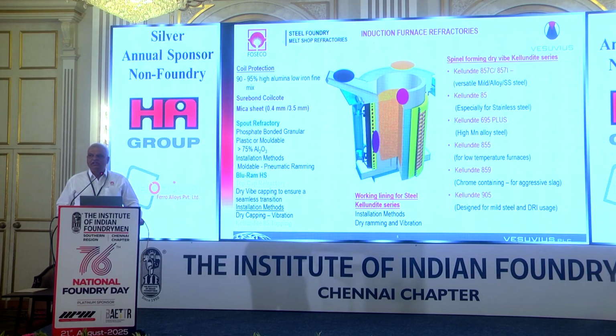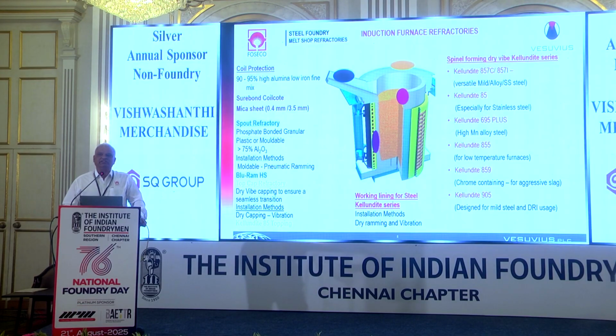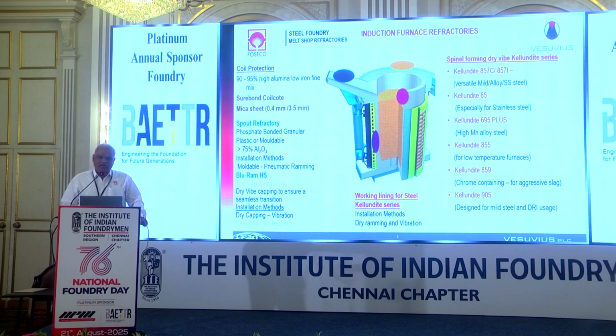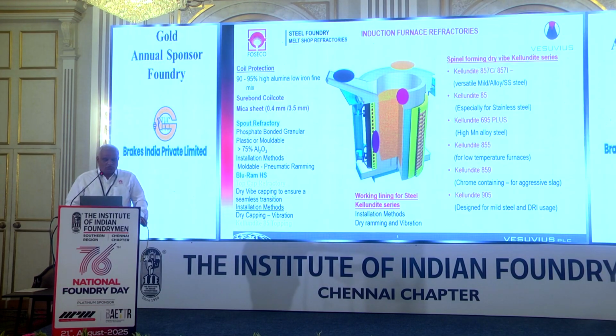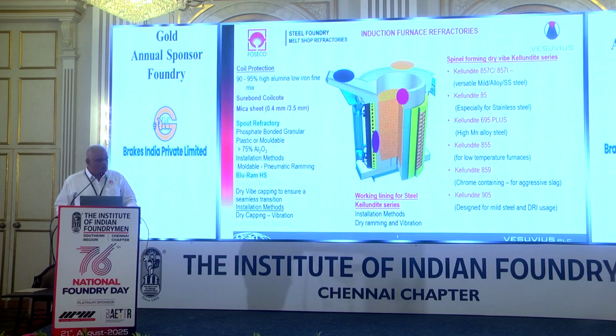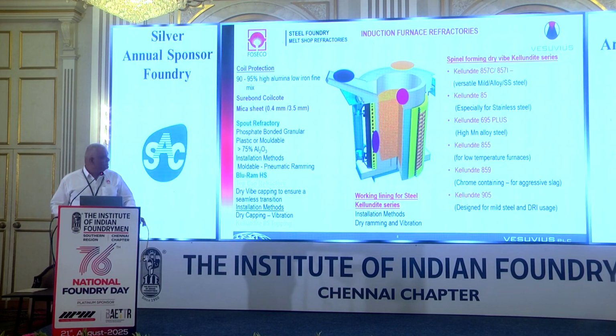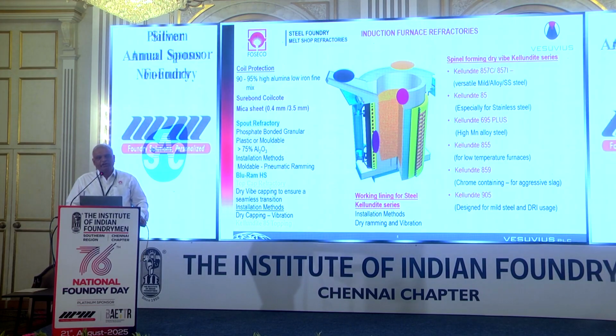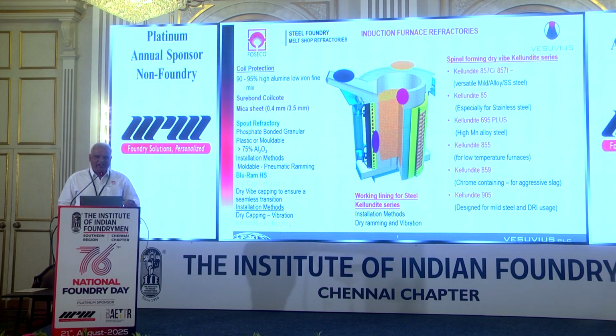They just sieve it and use it as a coil coat, but it is not advisable because in conventional castable the iron percentage is on the higher side. As this material is close to the coil, it requires lower Fe content and higher aluminum content. So this coil coat was developed, which has more than 90-95% alumina and low Fe content. Another refractory used in the induction furnace is for making the spout and top block. We have developed a plastic material, called a ready-to-use material, which can be used for making the spout and top of the furnace.